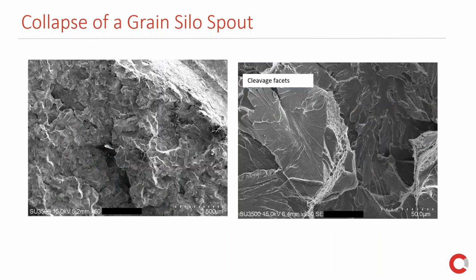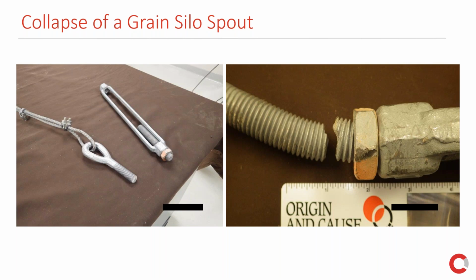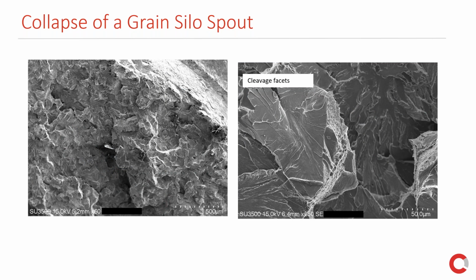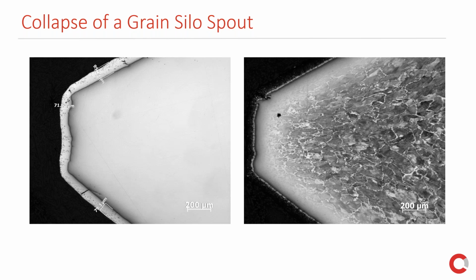So again, we provided a testing protocol to examine the turnbuckle. And that involved metallurgical evaluation of fracture surface analysis and chemical analysis. These images are taken under a scanning electron microscope, and they show relevant features of the turnbuckle. And in plain terms, it shows it was a brittle failure. But because the turnbuckle was heat treated, this fracture mode was considered not an issue.